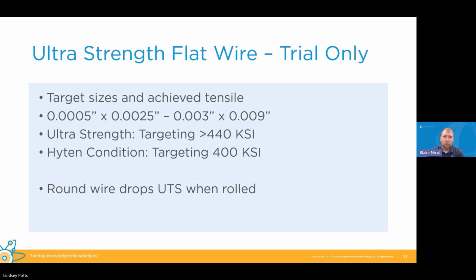We also are trying to explore the ultra strength process with flat wire. One thing to reiterate at the start is that flat wire and round wire have a different kind of cold work. So anytime we're rolling flat wire, we're going to lose strength from our incoming round wire. If we're getting 500 KSI, we'll probably lose about 50 KSI approximately. It just depends on the condition and what we're trying to manufacture.